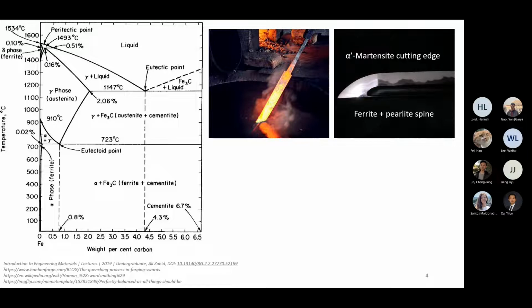Okay. The other way you form martensite is when you have metastable austenite. So this austenite phase stabilized down to room temperature. And say metastable because if you give it a bit of stress or you give it a bit of strain, that gives it the energetic kick to form martensite at room temperature. And that is a very gross oversimplification of the TRIP effect, or the transformation induced plasticity effect.